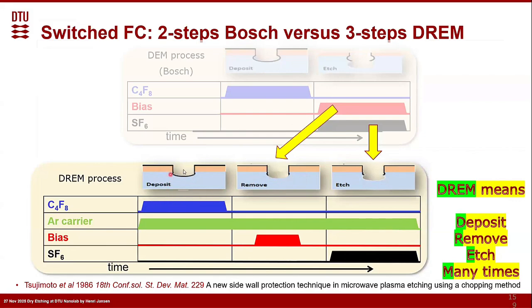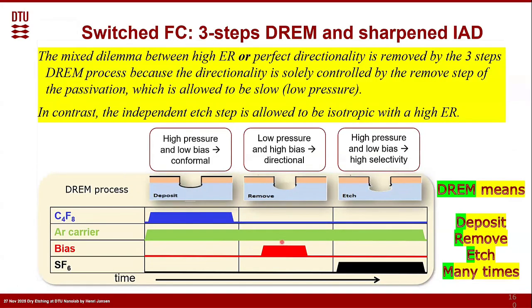So we deposit the layer, and now we have a step which is solely removing it at the bottom, but then we can take it away because after that we're going to etch, and that's again a spontaneous process with only radicals, and the silicon will etch isotropically, creating undercuts. That means we have created an even higher selectivity. And that's another part which is now becoming important, because the dilemma between high etch rate or perfect profile is removed by this three-step process, because now we can use a high pressure at the deposition, and there's no bias, so the mask is preserved.